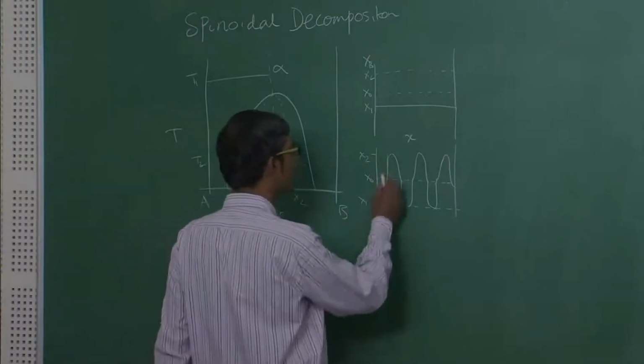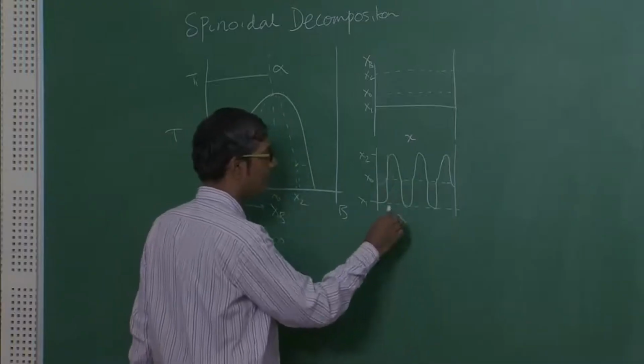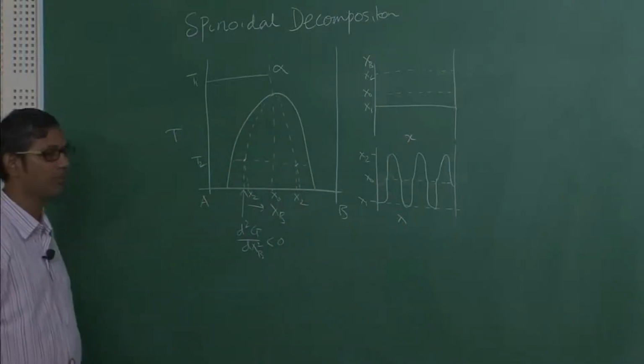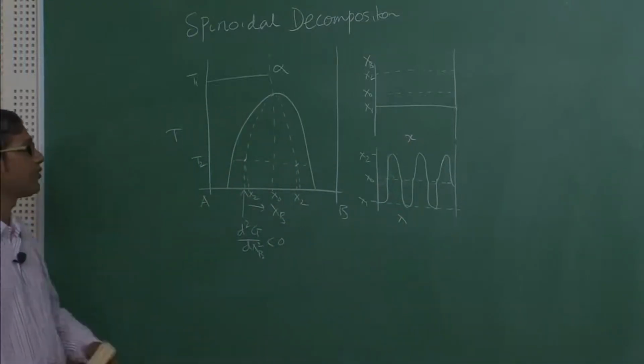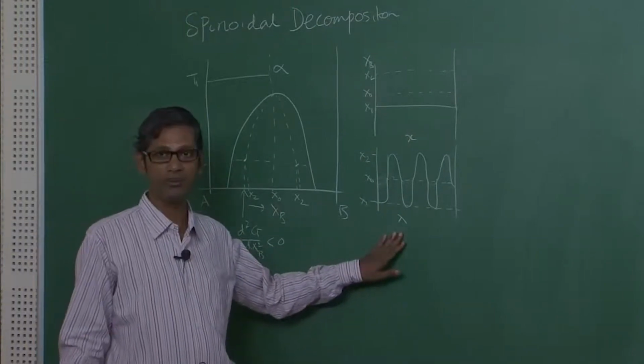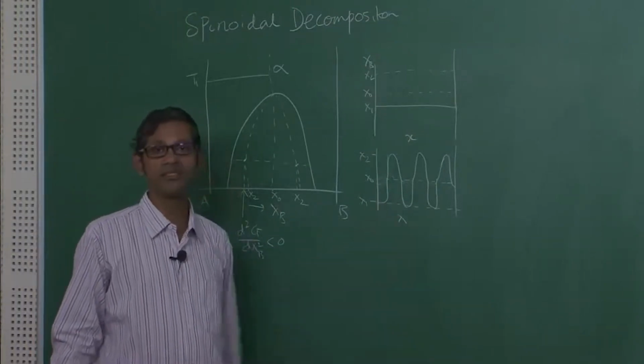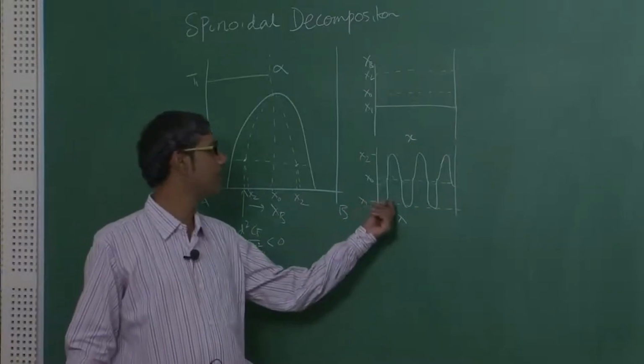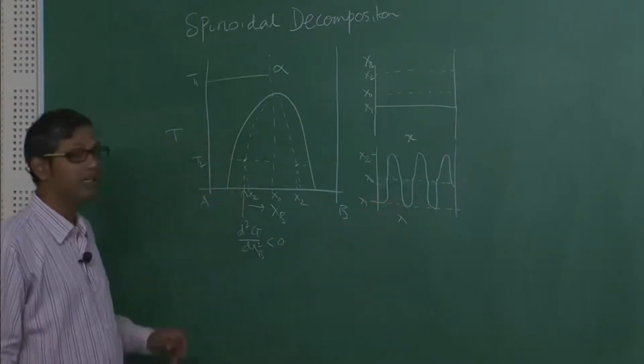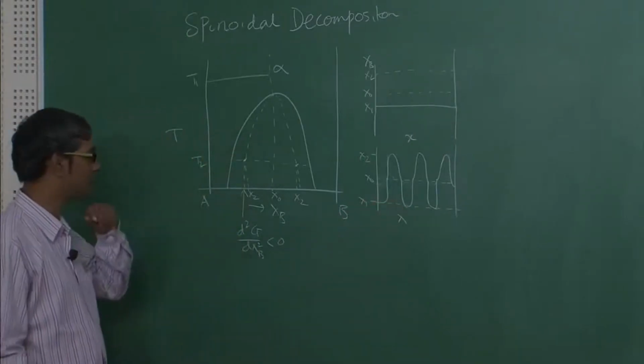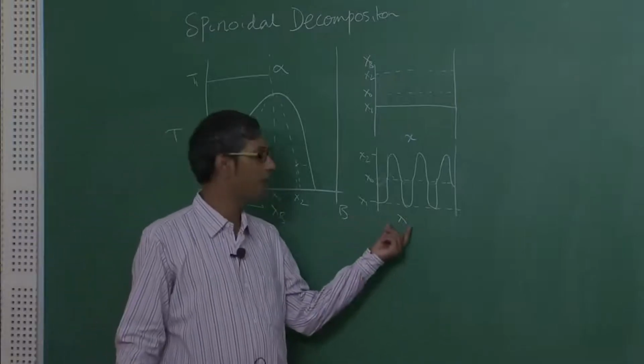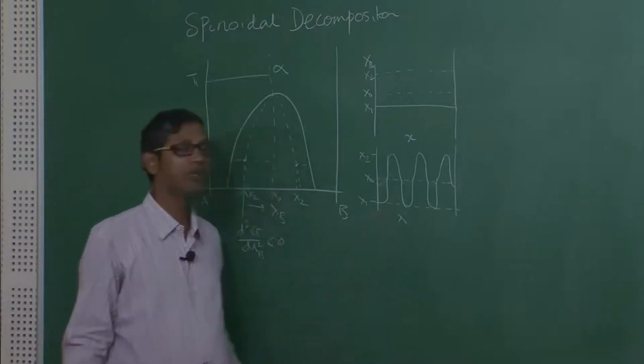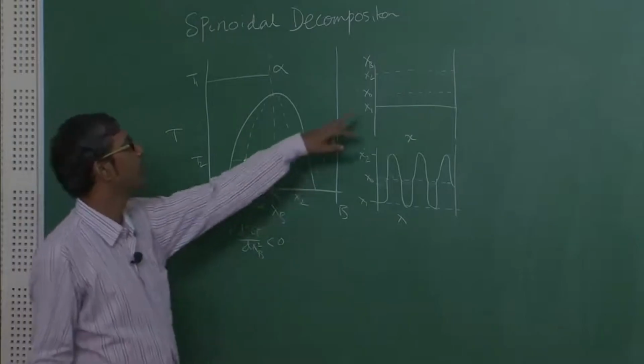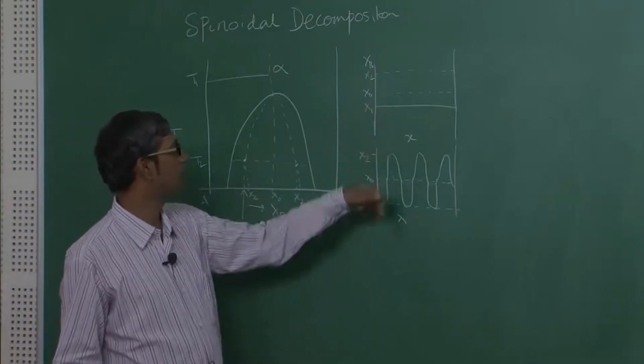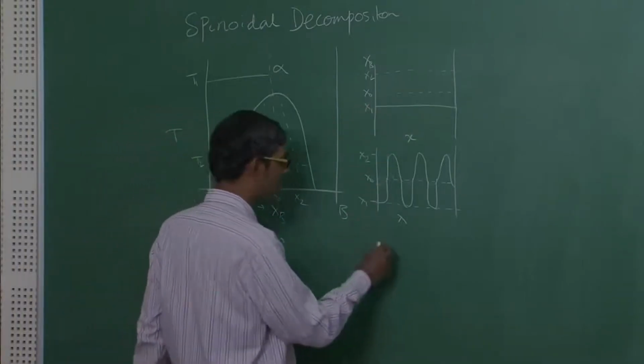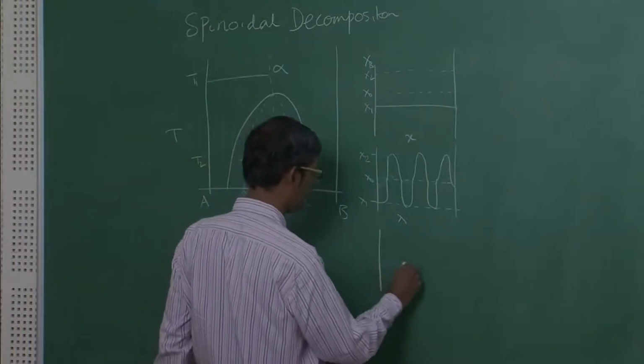As you clearly see, there is a particular wavelength lambda we can assume for this compositional fluctuation. Now, how can we determine the minimum lambda possible? As the lambda decreases, the wavelength will lead to an increase in the interfacial energy of the system. Therefore, there will be an optimum choice of lambda by which this decomposition from the composition of alloy x0 to x1 and x2 can happen. Finally, at the end this will be like this.